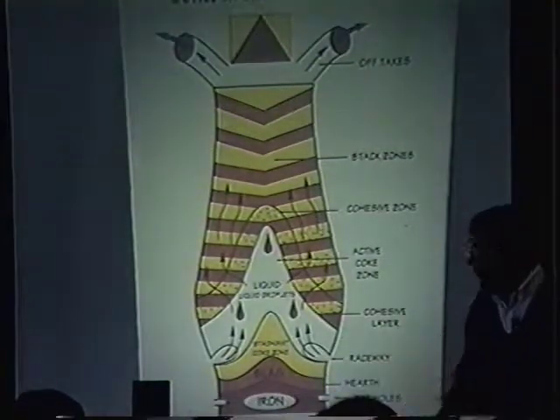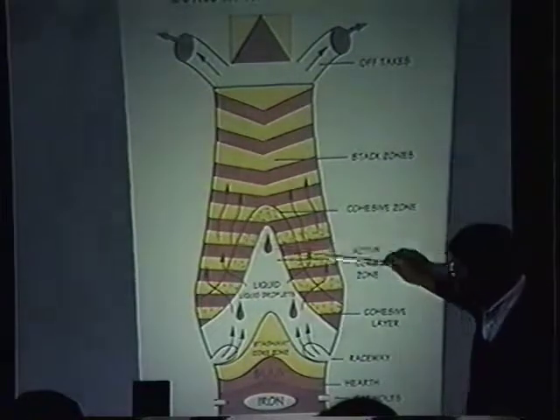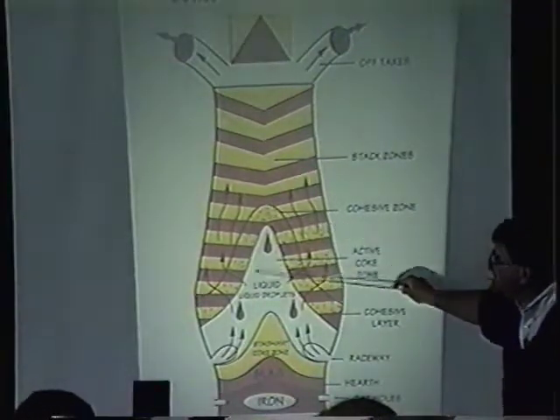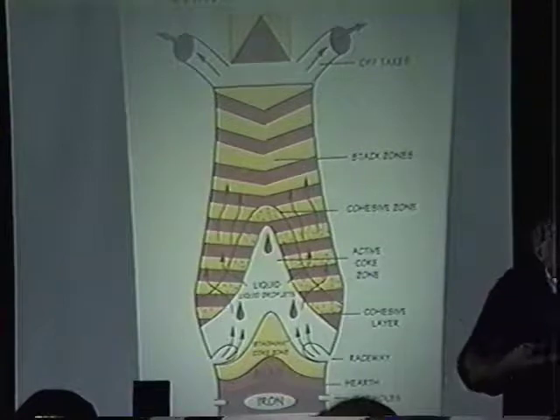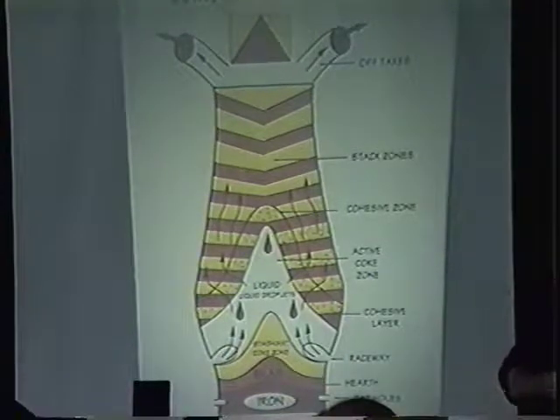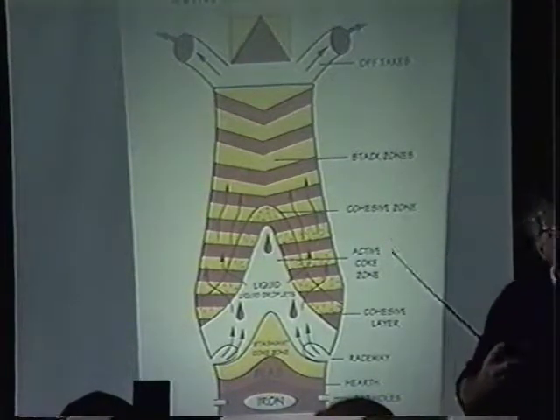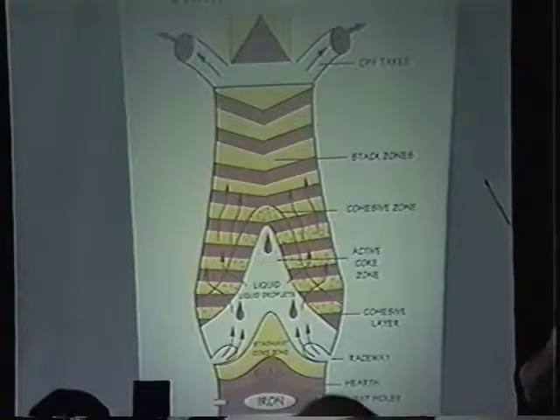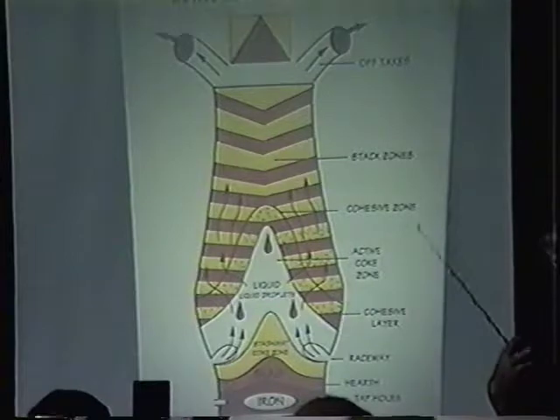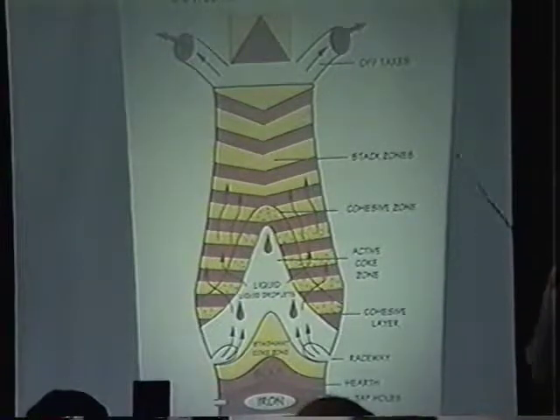Okay? And as this material comes down, it gets into this cohesive zone, or this active zone, where the temperatures are in the 2,000 degrees, 2,500, 3,000 degrees. The iron ore is starting to melt, or smelt. It's mixing with the fluxes, and we're making a liquid product.